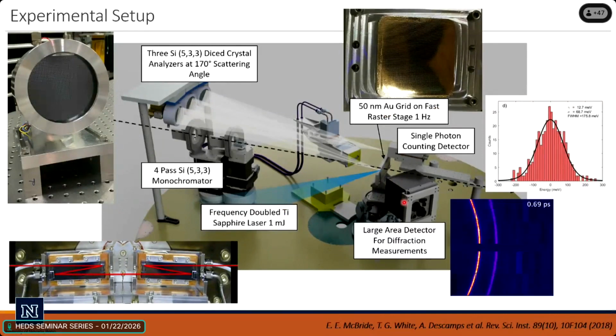Because there's X-rays coming in and hitting the target, for free, you might as well put an X-ray diffraction diagnostic in there and get the X-ray diffraction at the same time, because you get that for free, since you are X-raying, sending X-rays towards your target. So here you see the diffraction lines of gold, and then as it melts, as it heats up in the picoseconds after the laser pumps the system, you see the diffraction lines sort of vanish.